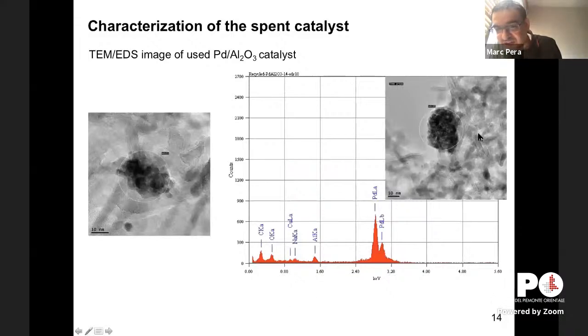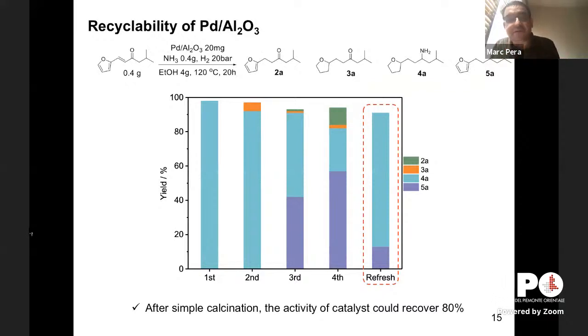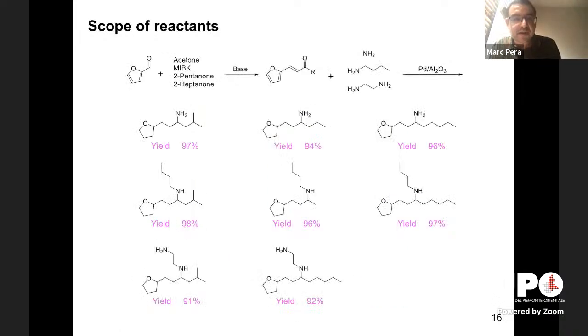Sometimes you don't see a lot, but small rocks like this. So amines tend to agglomerate the palladium. This is something that has been well studied. However, if we optimize the conditions, we can have decent results in terms of recyclability. And when we put in fresh catalyst, somehow we can recover the catalytic behavior.